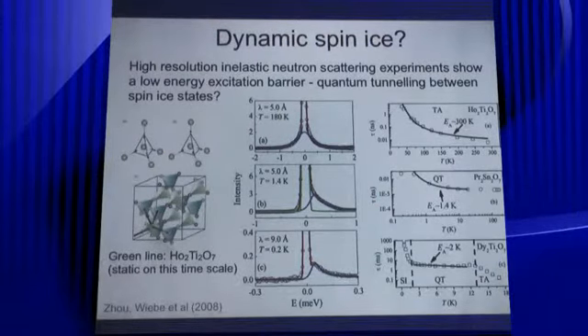And if you look at the gap for this, it gives you roughly 1.4 Kelvin. So that reminds us of the gap that's seen in dysprosium titanate. So for dysprosium titanate, if you look at this AC susceptibility data, you can call this the monopole region now if you like, but at high temperatures it has this thermally activated region looking at crystal field excitations. Then it has this flat region where it has an anomalously low activation energy barrier, so that's interpreted as quantum tunneling between different states before it becomes monopoles. And then you have this anomalous rise at lower temperatures. So our original idea was that we had some sort of quantum tunneling between these 2-in, 2-out states.